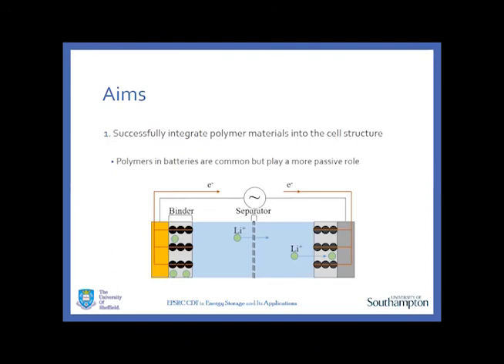During heating events, liquid electrolyte tends to form gases, or the organic elements decompose into gases, which increases the pressure buildup, which causes increases in temperature, which further exacerbates the thermal runaway problem. So polymer electrolytes are potentially good at avoiding that. It also removes the toxic and hazardous chemicals inherent inside of the liquid electrolytes themselves.